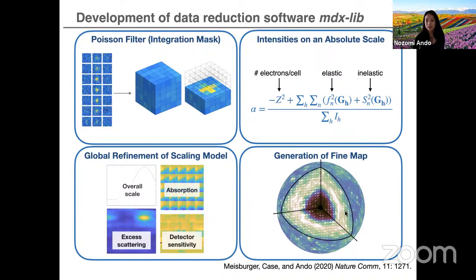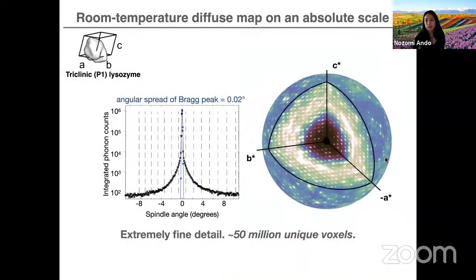You can think of this as the second Death Star. And just zooming in here once more, this is the diffuse map from triclinic lysozyme. So this is hen lysozyme. And the triclinic crystal form is the lowest symmetry one. That was useful, the fact that it was low symmetry. And the key reason why it was useful is because there's only one protein per unit cell. And that means that we have very small unit cell dimensions in real space, which translates to really large dimensions in reciprocal space. And by separating out the Bragg diffraction, we could see a lot of the features in between.